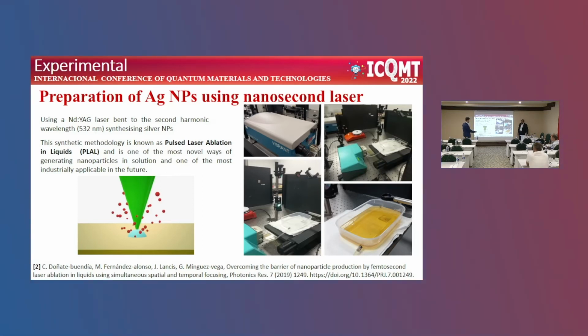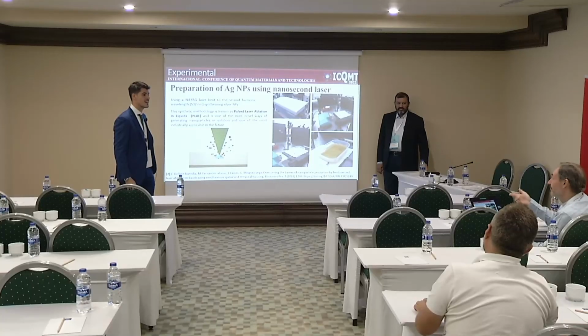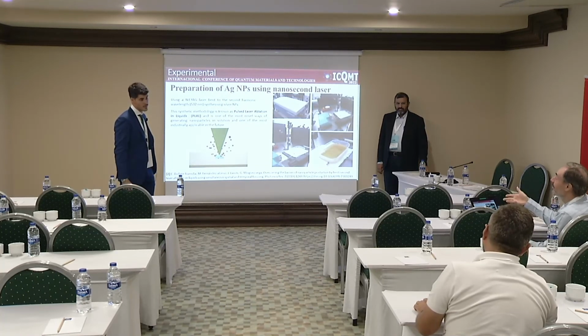You have, for example, this article that explains this type of production of nanoparticles, and you have here an expert for this type of production. Also the green wavelength is very good, because silver and copper are highly reflective with the IR wavelength. But with the green, because of the plasma effect, they are much more absorbing, much less reflective, so it's very efficient. Especially with the femtosecond laser, non-linear effects give you much more absorption.